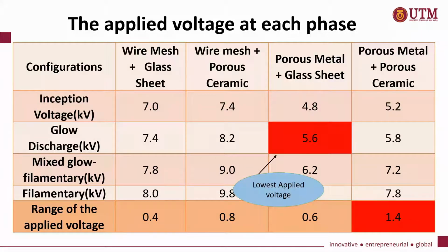Then we can also see that the configuration with porous metal as electrode and porous ceramic as dielectric has the largest range of applied voltage among the other configurations. This result further strengthens the conviction that the porous alumina ceramic can help in sustaining a stable and homogeneous glow discharge plasma due to the existence of the micro-holes.